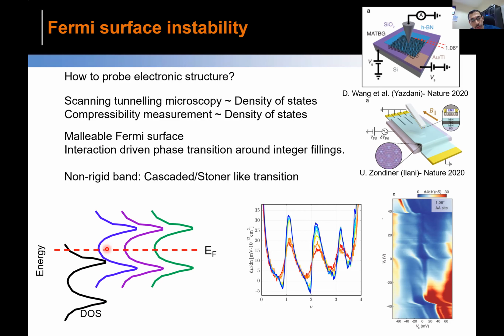As I dope the system, one of the flavors completely fills this band, but the others become completely empty. And this process becomes repetitive between the second and third, and third and fourth. This is known in the literature as the Stoner-like transition and cascade transition. This transition you cannot explain by the single particle picture, which is the MacDonald calculation, that continuum model. You have to calculate this.